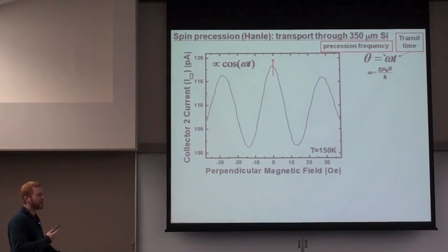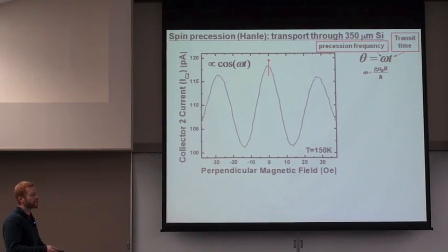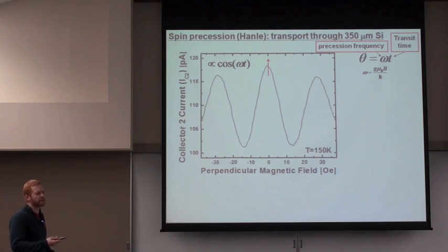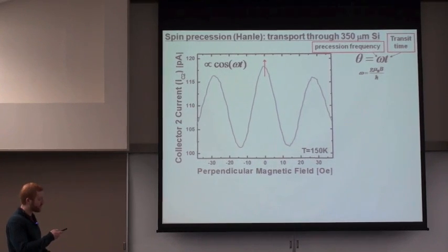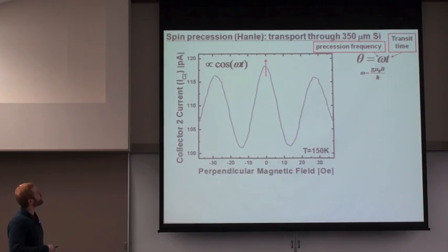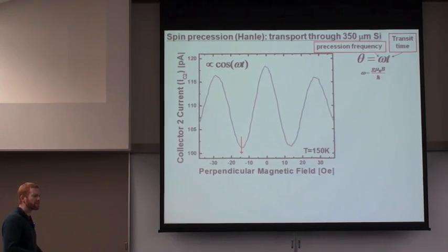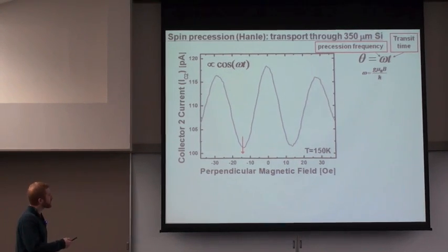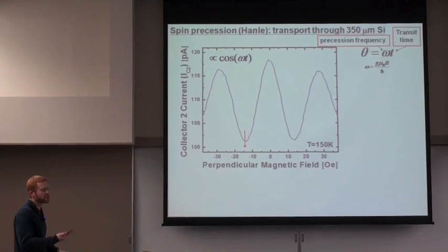So the idea here is that if we have parallel injector and detector magnetization, then at zero applied perpendicular magnetic field, there's no spin precession. And so we have a relatively high spin signal. But if we apply a very small perpendicular magnetic field, due to the very long distance between injector and detector, we can arrange it so that we inject spin up, but we have precession of 180 degrees by the time it makes it to the detector. And so even though we're injecting spin up, measuring spin up, in the absence of precession we would expect a large signal. But because the spin is rotating from up to down, we get a low signal at just about 10 or 15 Gauss.